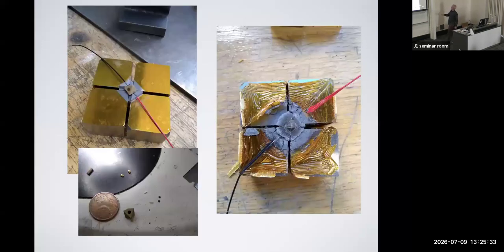And here's the assembly, right? So these are tungsten carbide anvils here that have a truncated edge. And at that truncated edge sits the actual furnace assembly. And these are not standard tungsten carbide assembly, right? That's the other part. Standard tungsten carbide is one of the hardest materials, short of diamond. These are special sauce Japanese tungsten carbide doped with cobalt and all sorts of other things that can sustain the pressure and the temperature, right?